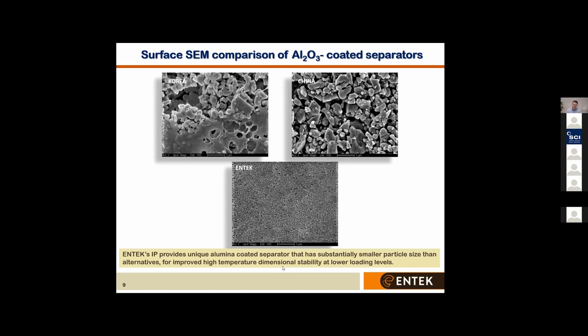As we know, not all lithium-ion separators are the same. In the upper left is an SEM of a typical SRS-type separator, where the ceramic and adhesive is mixed in one layer and is the preferred separator system for LGES. On the right, we have the larger particle structure, predominantly boehmite, from Chinese suppliers. And then, as you can see, using the same 1 micron gradation on the SEM, you can see the substantially smaller particle size and homogeneous nanostructure of the ENTEK coating IP, which is actually the IP that we intend to onshore in the UK.